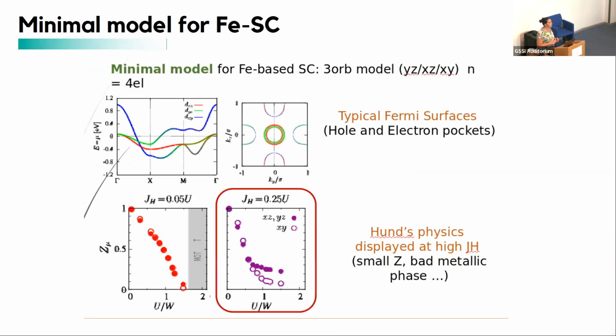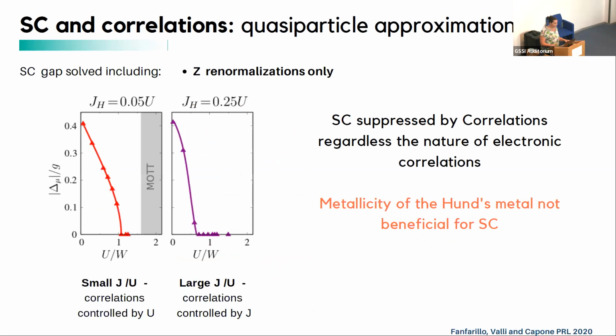The model that I'm using is a pretty small, minimal model with only 3 orbitals at the Fermi level, but this is enough to reconstruct essentially the features of the bands close to the Fermi level and the topology of the Fermi surface. I'm going to show you results for 2 different values of J. You see that these show exactly the physics that I mentioned before. For J equals 0 or close to it, the renormalization of the kinetic energy goes down and you have a metal-insulator transition. For high J, you have this tail and the state remains metallic. So these are the results.